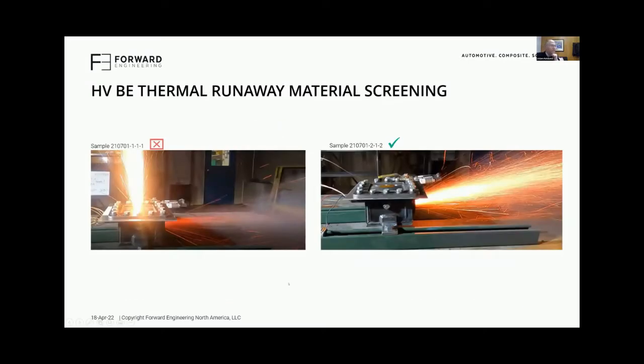And here's the fun stuff. This is not what you want to see. So in the event that the sample does not endure. Now, having said that, not what you want to see, the reality is we want materials to perform good enough. So sometimes when you're running the samples, you're going to push the limits of what those samples can do. And that's what you're seeing here, a sample material which did not withstand the pressure, the energy that was imparted on that sample. On the sample on the right, you can see a material that did withstand that energy imparted upon it.